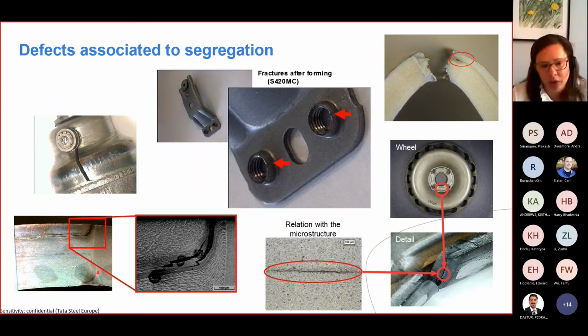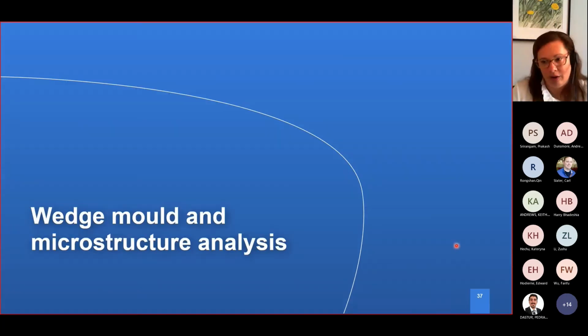This is a welded tube, part of a welded tube. In this case, it is on a quarter band where a crack has been associated to highly segregated areas. And in the middle of the tube, or the strip itself, the central segregation is seen. So if we compare this with another area which has not segregated at all, the unevenness makes this even more obvious. Here, for example, is another example of a wheel, which while forming it, has opened like a book, really. And this is associated to central segregation. So the strip itself has opened up in two. Well, honestly, I'm not sure about you guys, but I don't want to have this in my car. I don't want to drive a car with this kind of wheel, really. So I want a better one. That's why we do it.